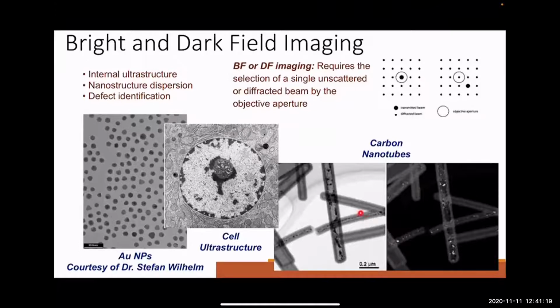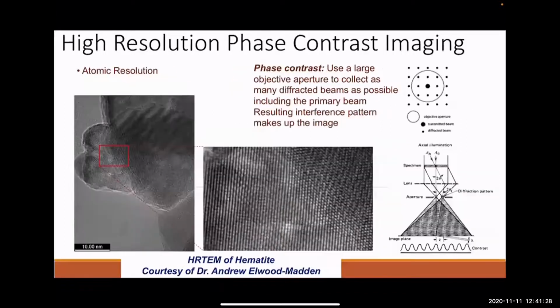So for example, here's a bright field image of carbon nanotubes. Here's the dark field image, and the little catalyst particles are glowing or shining bright. You can take it even further, down to the full atomic level, and this is usually considered a different imaging mode, because you're trying to collect not only the unscattered component of the beam, but as many scattered components as possible. They will all combine. This is called phase contrast, and it involves constructive and destructive interference, and what you get is a series of bright and dark spots on your image that you can interpret as atoms.